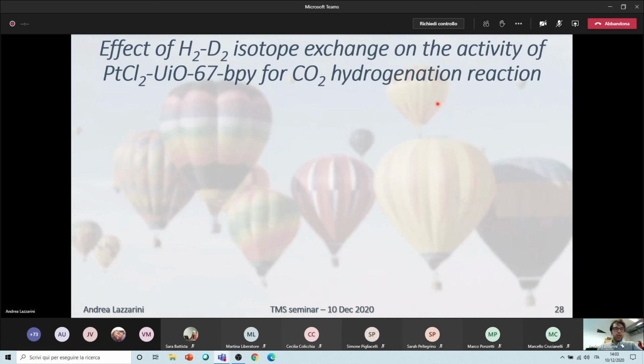So in order to check the reaction mechanism that is producing CO, we were trying to make some isotopic exchange experiments. So instead of using hydrogen as the reducing agent, we were using deuterium. So basically it's just hydrogen with a neutron more. So it has exactly the same chemical properties, but a different weight and mostly a different infrared signal. And therefore, we checked with the GC system what was happening to the system, and basically we were ending up with just CO and few, let's say, molecules of methanol and methane.